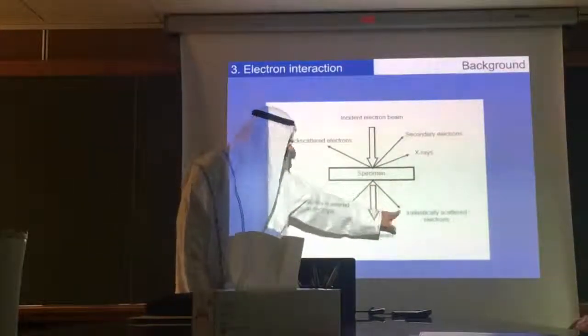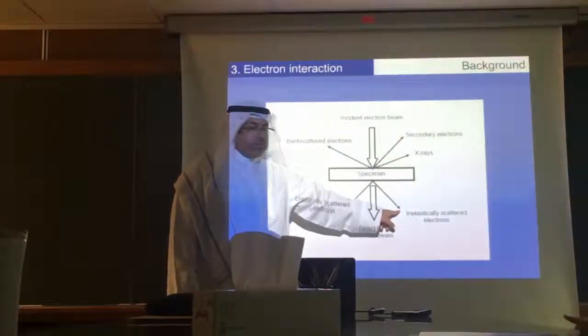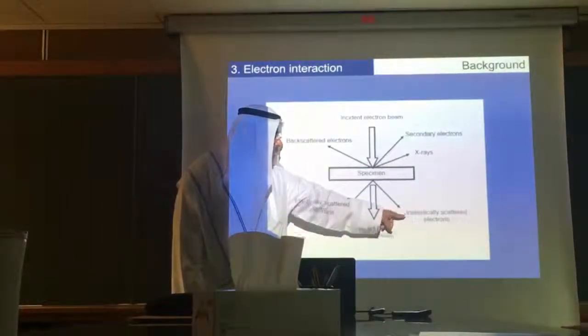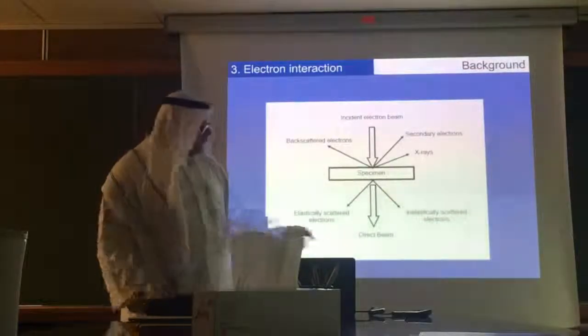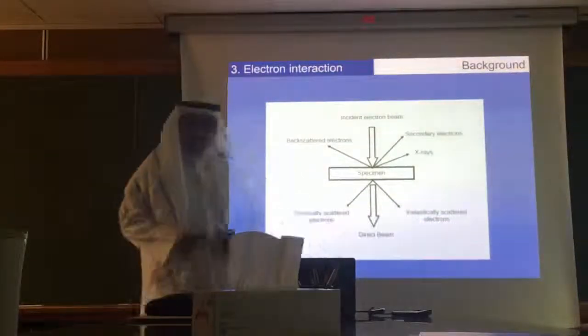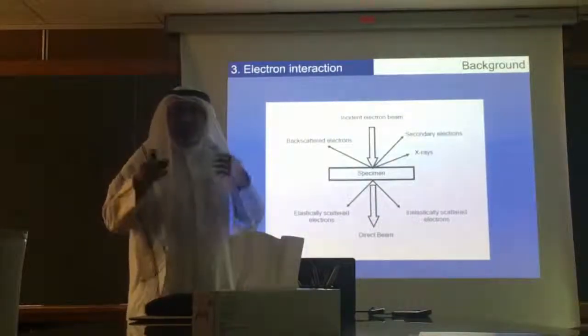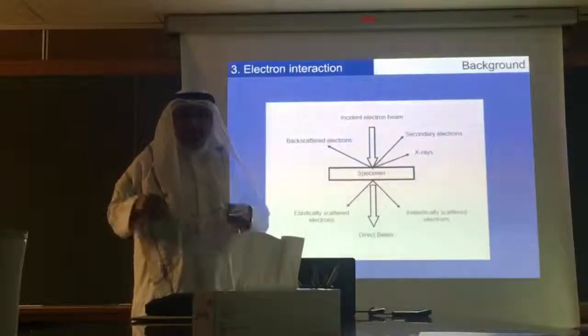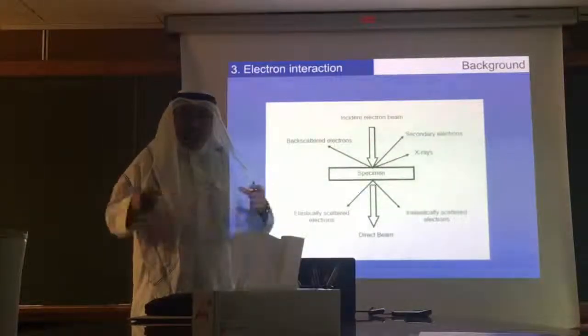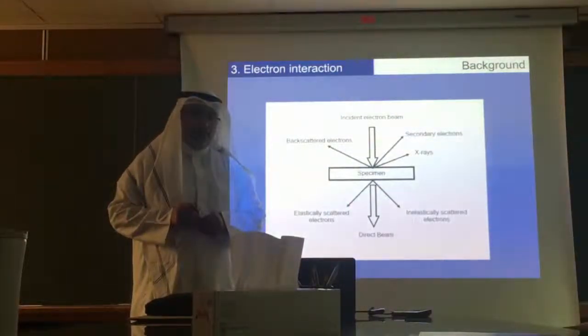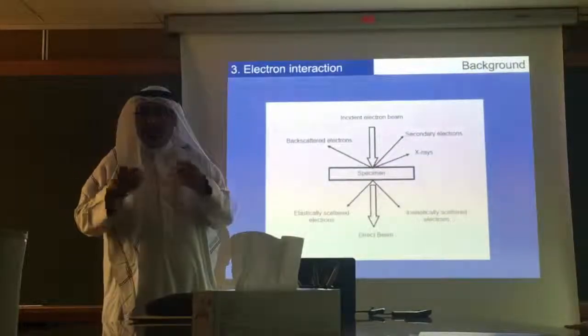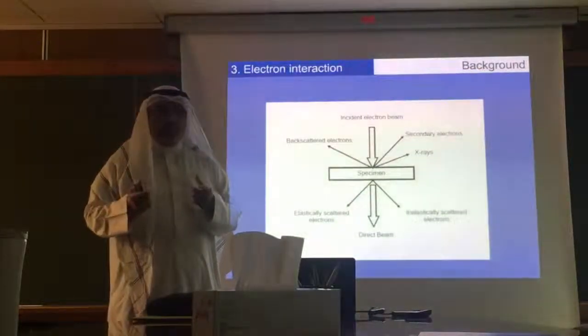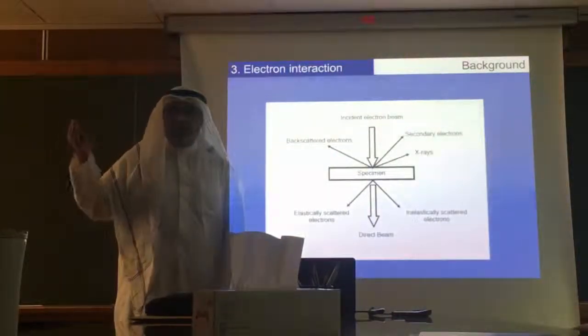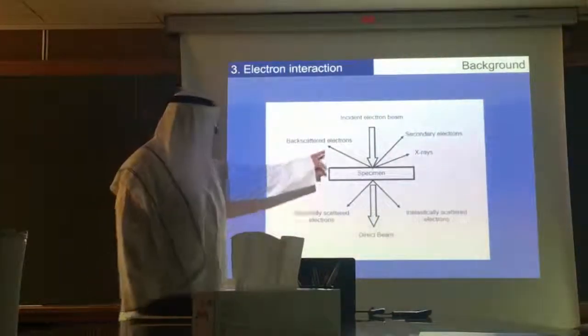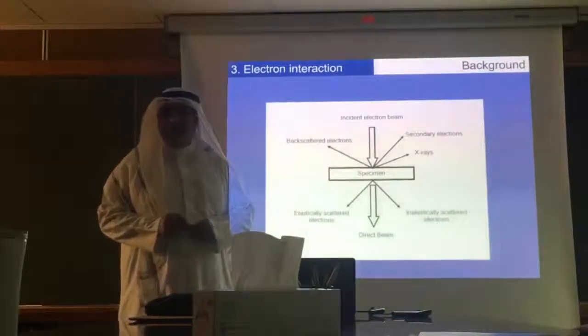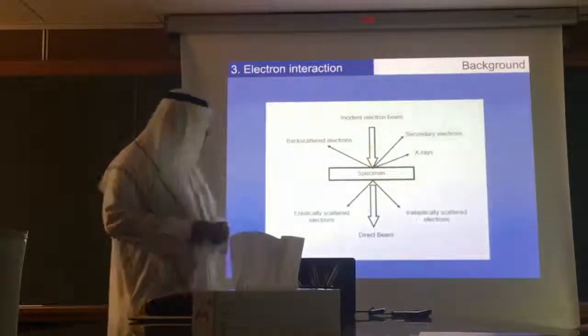If you have a very thin sample, some signal will escape from these samples and result in something we call elastic scattering of electron. This is actually related to the transmission electron microscope. It has much higher resolution than SEM, much better, because the column actually has many different lenses and has apertures. We call them objective apertures. So you can control the resolution and enhance it much better. And you can increase the electron energy to 200 or 300 kV, while for scanning electron microscopy, we can only have up to 50 kV or 80 kV maximum.